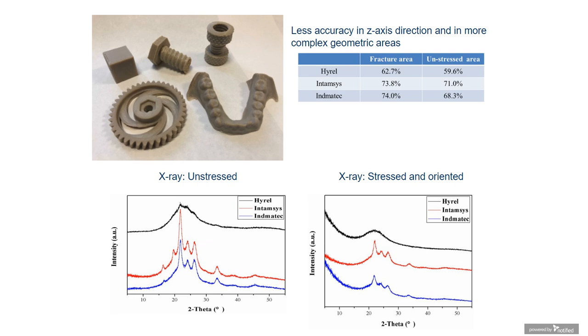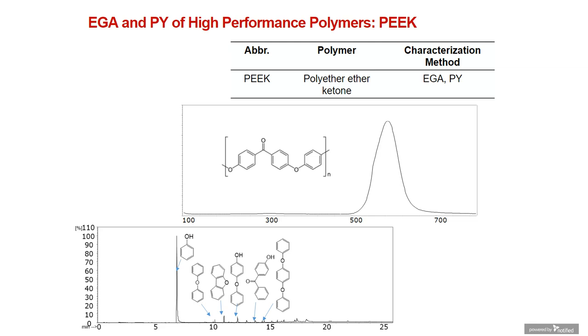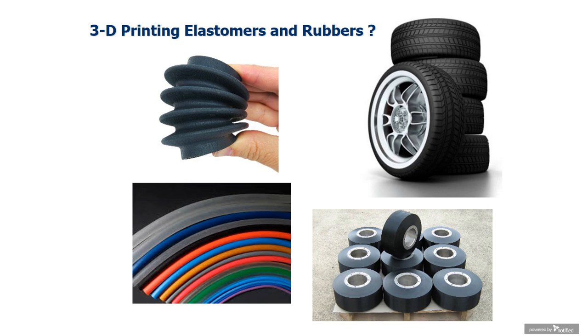The bottom line is we published this work, and without GC mass spec pyrolysis, we would not have been confident in reporting their properties. What GC mass spec pyrolysis did is it confirmed quickly, based on EGA, that we have a very high purity polyether ether ketone. Not much additives or none are present. This was processed at a high temperature as a filament, and the typical signatures for the structures associated with PEEK were observed in the mass spec. So very quickly, EGA and pyrolysis allowed us to confirm and confidently report on a commercial sample in a publication.